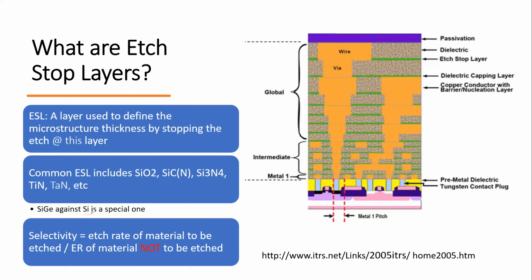You put usually a dry etch, or could be a wet etch, but usually it's a dry etch. And you etch through something, and you will stop at a certain layer. What you hope is that the etch rate of the material not to be etched is very, very small, and the one you're going to etch through is very large. Selectivity is a ratio that is, as high as possible, I suppose.